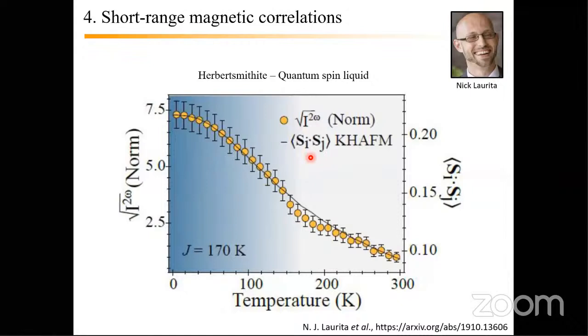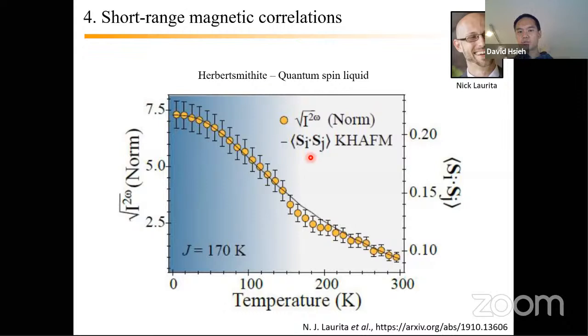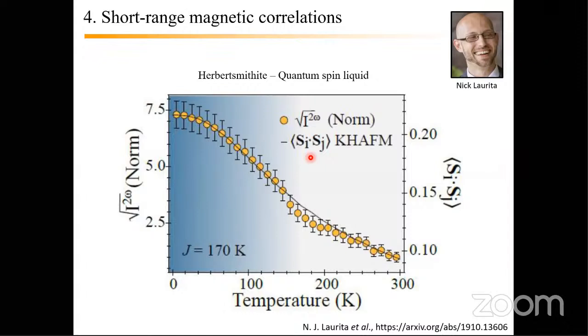But do you always monitor the intensity of the second harmonic against the intensity of the input beams to see if it's simply going quadratically or with some other power? Yeah, that's really important. If we're claiming second harmonic, then we always check that it's quadratic dependence. At higher power sometimes it deviates, so we make sure we're staying in the ideal regime.